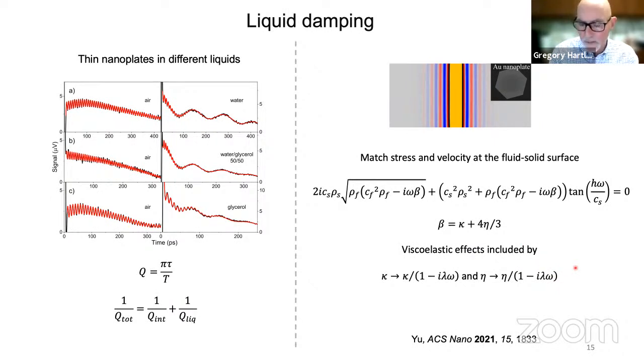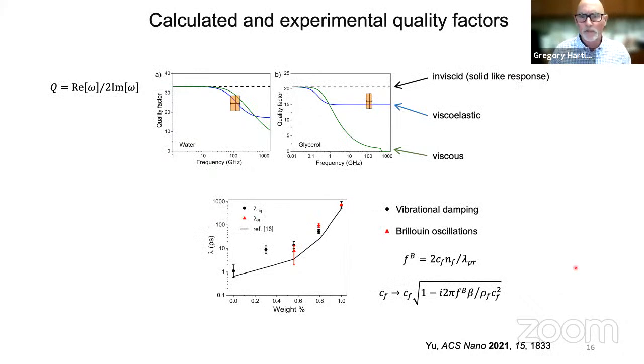viscoelastic effects. All right, and so this is the result of the calculation. The lines are these different calculations. The solid line is leaving viscosity out, so the liquid just has a density and the speed of sound. The green line is including viscosity, but leaving out the relaxation time, so leaving out viscoelastic effects. So this is a Newtonian liquid, and the blue line is including everything.